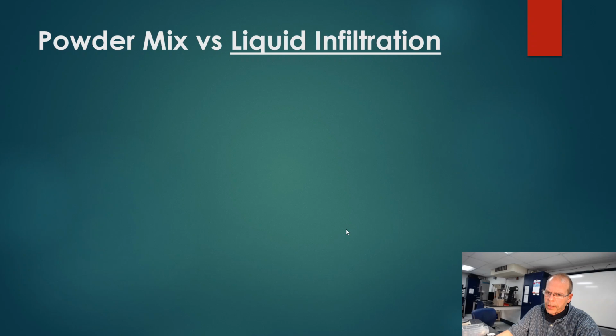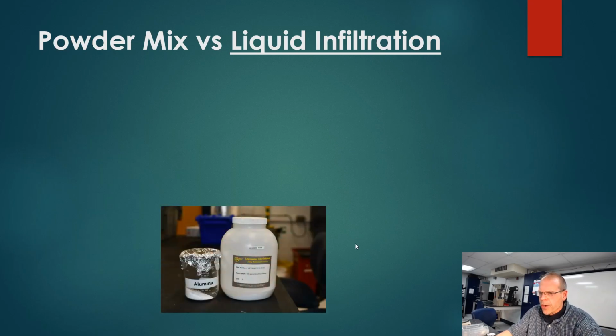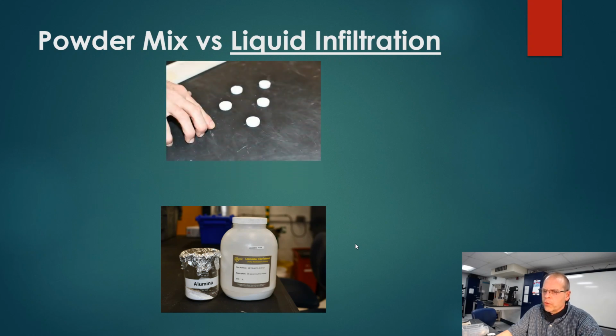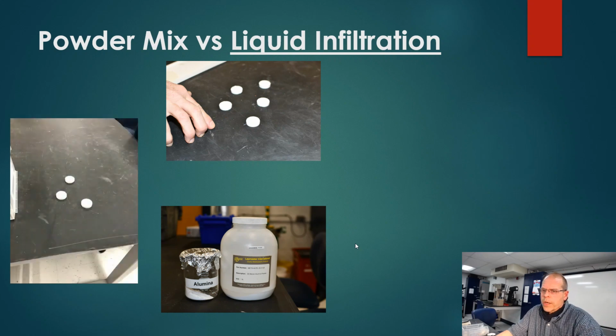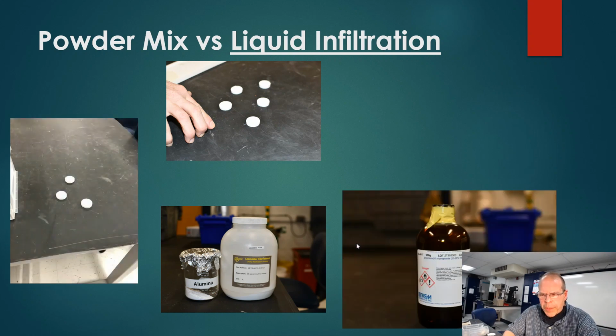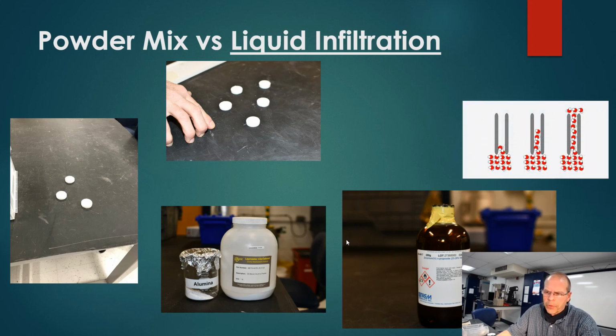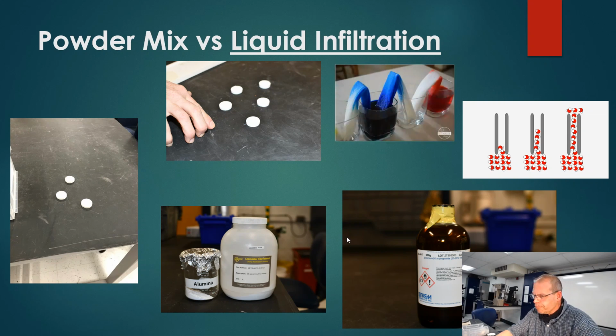The second way, a little trickier, not an exact science, and for 5 years doing this lab, I've tried to perfect it, but it still leaves room for improvement, is liquid infiltration. So we will start again with alumina, but this time we're going to take those green bodies we made in the second slide, just of aluminum oxide, and we're going to infiltrate a precursor, which is basically alcohol and zirconium oxide in a liquid form. And we're going to soak these together through capillary action and hopefully absorb a certain amount of zirconium oxide that mirrors the amounts that we have in our powder forms. Again, kind of tricky to get the right amount when you do these things, as you'll see.